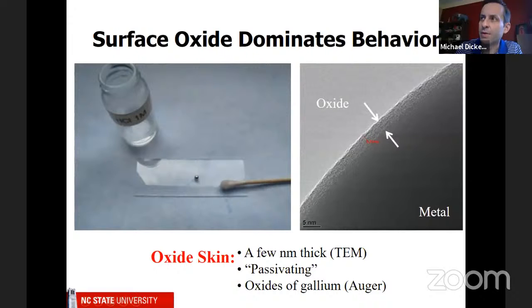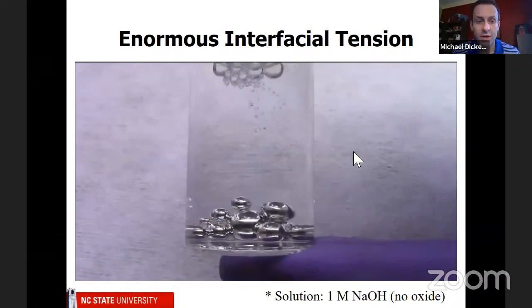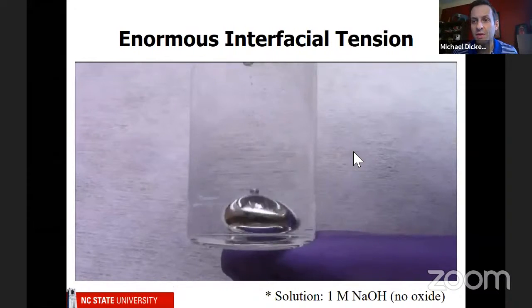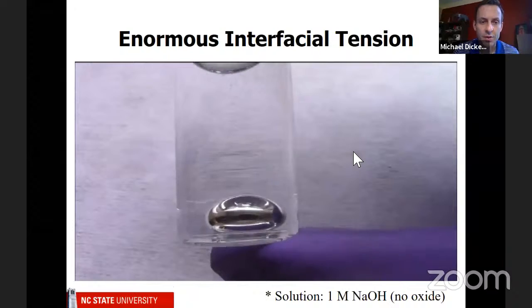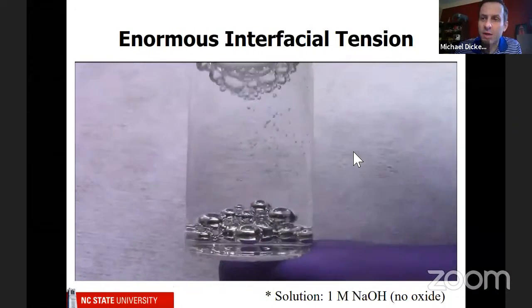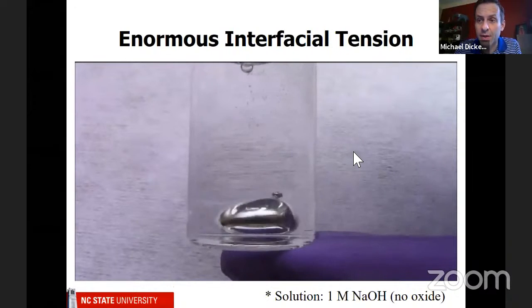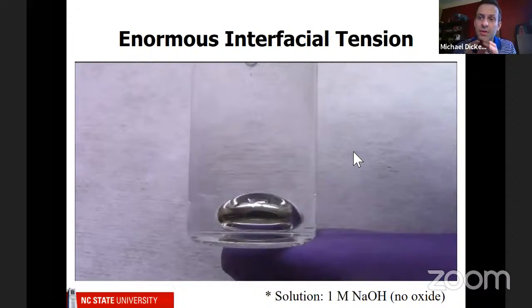And then you might remember that the liquid metal has indium in it to help lower the melting point, but the surface layer is just gallium oxide. So in the absence of this oxide layer, the metal has a very, very large surface tension. In fact, the largest surface tension of any liquid known to man. To illustrate this, this is in base, 1 molar sodium hydroxide, which removes the oxide layer. And when you shake this vial, I'll play it maybe one more time. When you shake this vial, there's enough energy to break the metal into little droplets, but it very quickly goes back together because one droplet minimizes the surface area and therefore minimizes the surface energy.